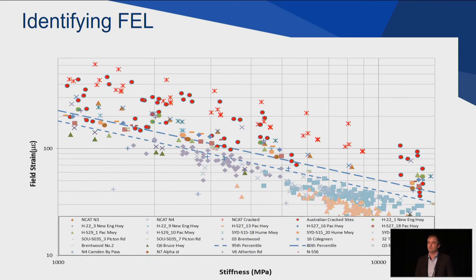That was identifying the fatigue endurance limit, and they looked at a very wide range of actual field performance data from across the world. So there are NCAT sections in there, there are outcomes of the UK Velman project, which basically looked at the whole road network in the UK, and then there are a lot of Australian sections there. All those sections have carried a lot of traffic for a long period of time, and what they were trying to identify was the boundary between which sections start to crack and which sections don't crack. That was expressed in terms of the modulus of the material and the fatigue strain, or the field strain, so the horizontal strain at the bottom of the layer as calculated for those sections. So they determined that boundary between cracked and uncracked sections, and then also came up with an 80th percentile confidence and a 95th percentile confidence limit for that fatigue endurance limit.